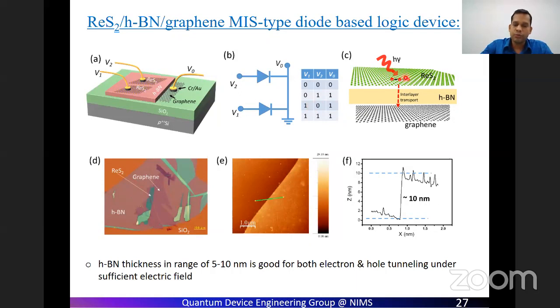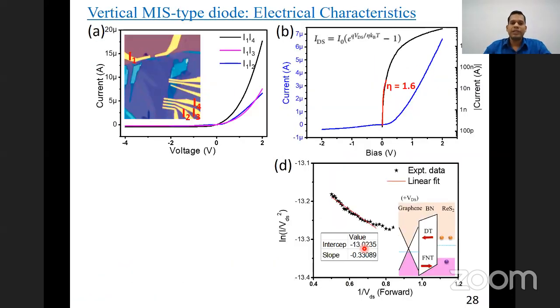And again, we can use light illumination to have a multi-value logic circuit as well. The optical image of this type of device is shown here, where we use a thickness of hBN of around 10 nanometers. This is quite good for both electron and hole tunneling layers under sufficient electric field. So initial characterization shows that each one of these parallel diodes can have highly rectifying characteristics, as shown from this IV diagram.